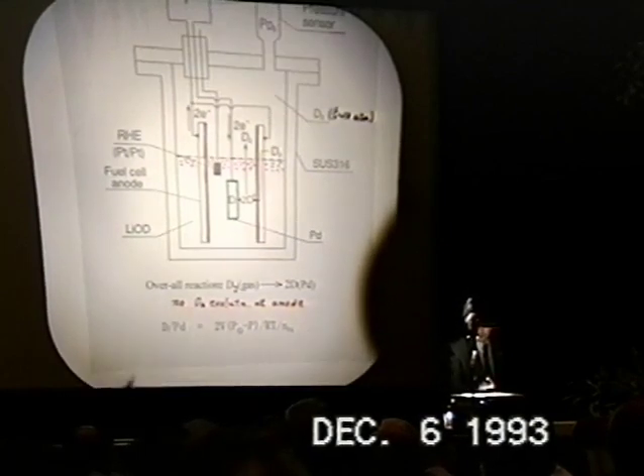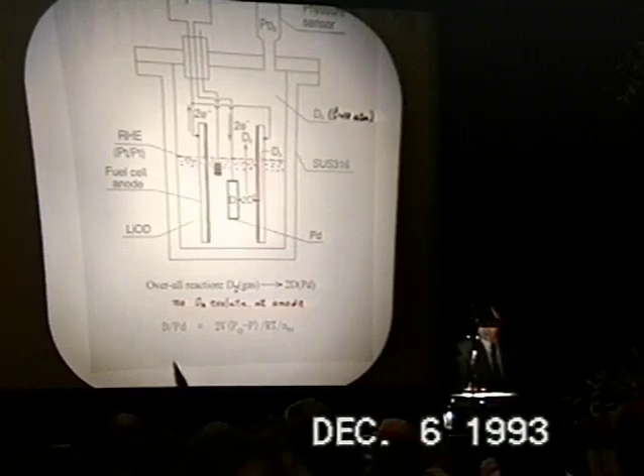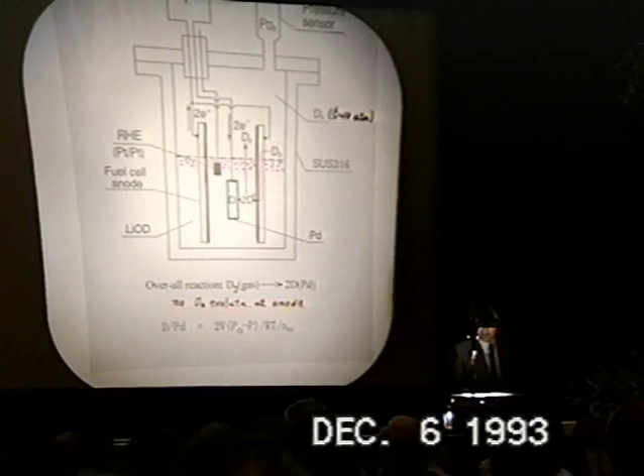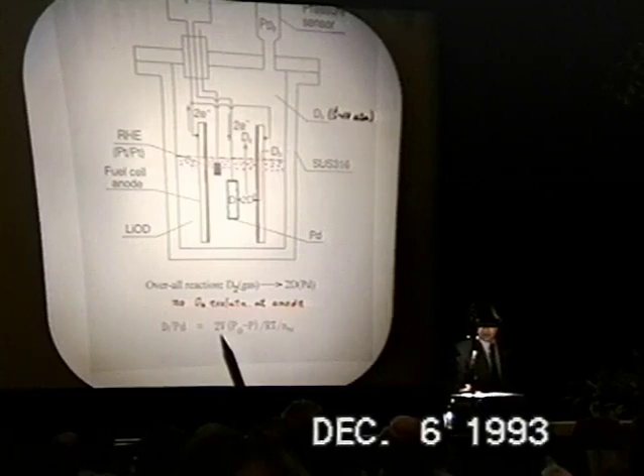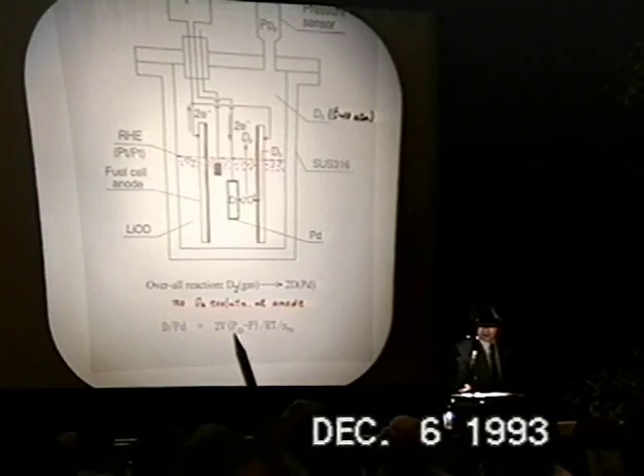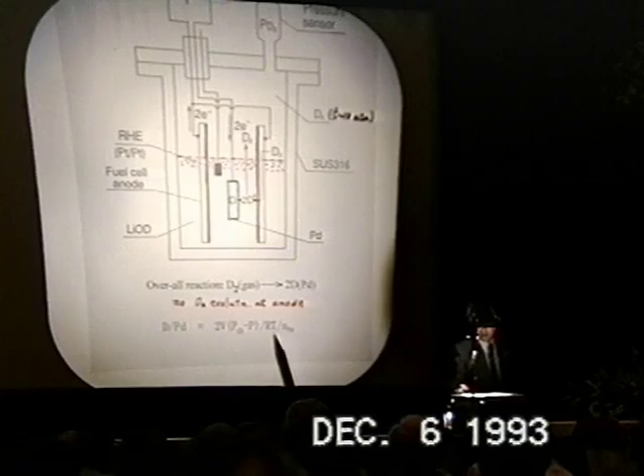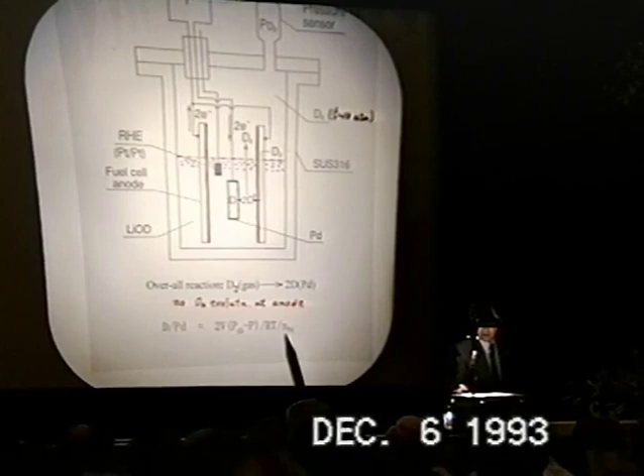And then we can calculate the deuterium loading ratio online from the pressure changes during the experiment, which is given by this simple equation, which includes the internal volume of the cell, the initial pressure of the deuterium gas, and then the actual pressure during the experiment, the gas constant, the absolute temperature, and the number of moles of palladium atoms in the palladium cathode.